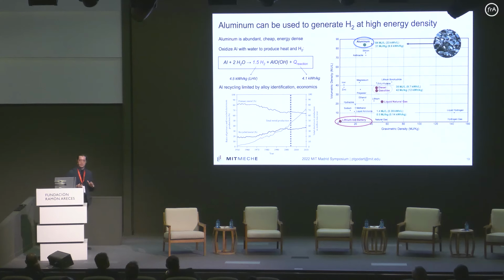So this research in particular is inspired by the idea that aluminum is abundant, cheap, and highly energy dense. Again, it's comparable in terms of energy density per mass, gravimetric energy density, joules per kilogram, but where it really excels is in the volumetric energy density. It actually has double the volumetric energy density of liquid hydrocarbons. And the way we extract this energy is by, as we do with all of these other sources on here, we oxidize it. And we can oxidize it with water by this reaction here that produces hydrogen, this inert and valuable aluminum oxyhydroxide, which I'll talk about later, and heat directly. And the embodied energy in that aluminum is released in roughly equal proportions between the heating value of the hydrogen that's produced and heat directly.